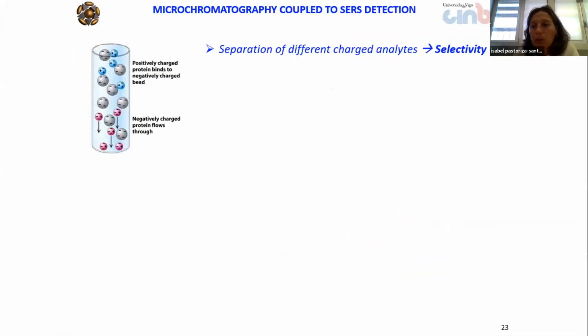But sometimes it's very interesting to try to detect selectivity for a certain molecule. So in order to check if we were able to achieve that with our microfluidic chips, what we did was combine the microfluidic channels with microchromatography. Microchromatography is based on the use of silica particles that are negatively charged, in a column, and when you pass a mix of positive and negative charge, the molecules with opposite charge are retained by the silica particles and just the molecules with a negative charge flow through. So this is the idea to provide selectivity to our sensor.